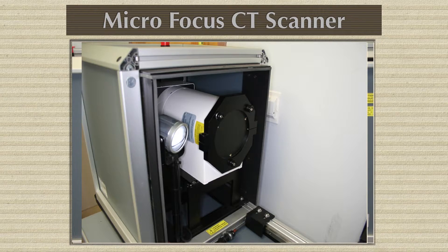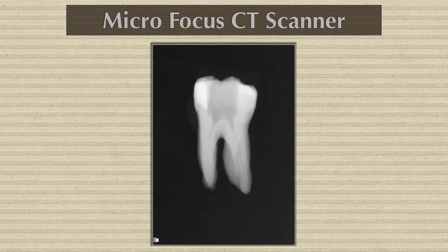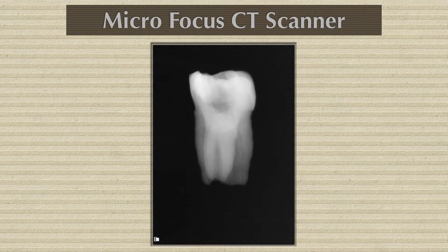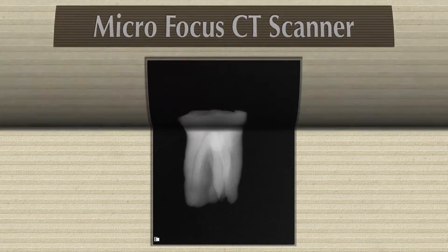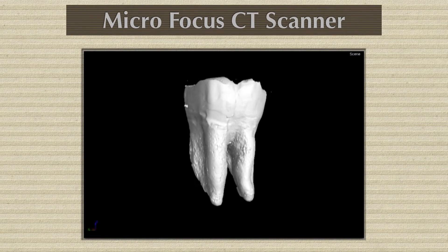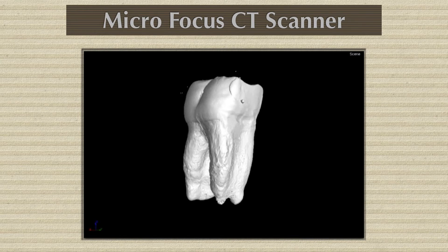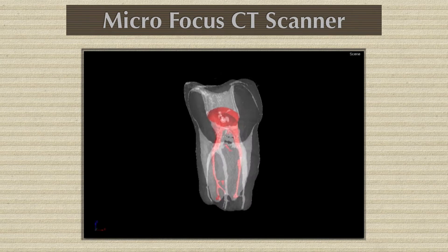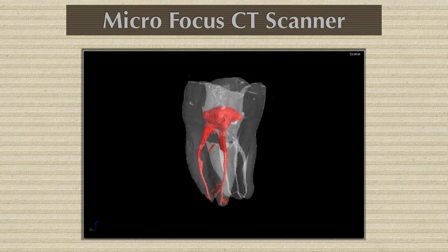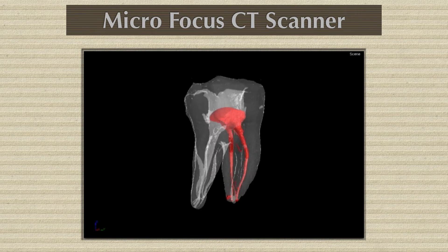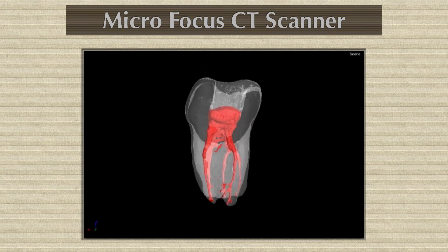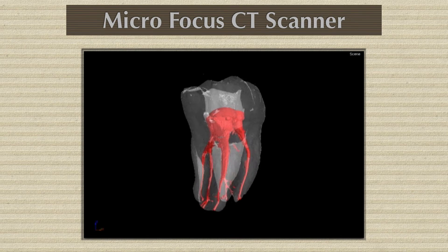That's the tooth in the stand, and this is the camera that captures the images — a fascinating device. When we were testing this technology, this is a tooth, and these are regular x-rays of it. When we scan and reconstruct the tooth, you can see it has five root canals. We can precisely quantify everything inside: CDC junctions, canal-dentin-cement width, canal dimensions before and after preparation, how much gutta-percha went into the canals, how much cement, and any voids at the interface between the canal wall, dentin, gutta-percha, and cement.